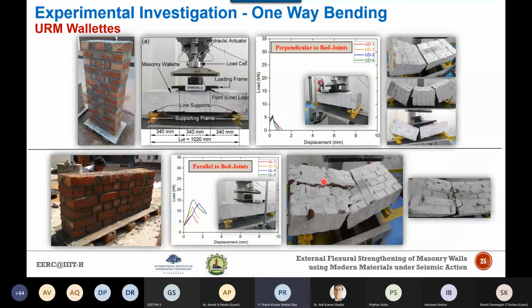So here you can see that in case of perpendicular to the bed joint, a sudden strength degradation and brittle failure has been observed once the cracking has been initiated. But when the same wallet has been constructed parallel to the bed joint, it has been observed that the cracking is initiated in the head joints and propagated either in a toothed pattern, or along a combination of head joints and bed joints. And why has this happened? This is due to the interlocking of the brick units.